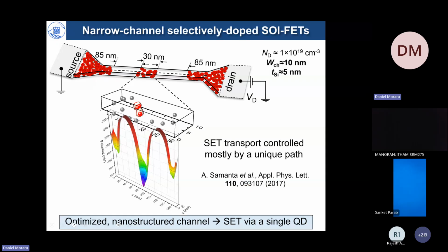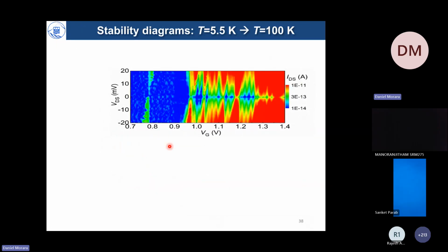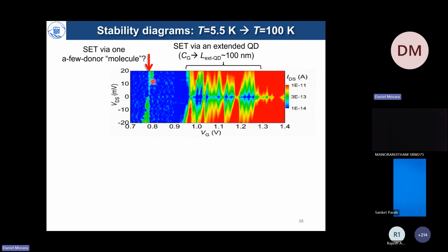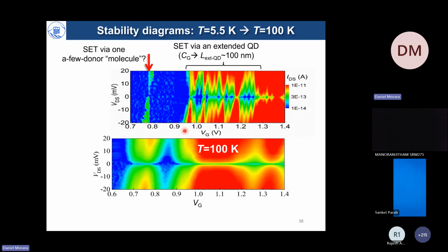So with this optimized and nanostructured channel, we actually started to measure the stability diagrams. By now, hopefully you understand that this is a map of the absolute value of current in the space of VG, gate voltage, and VD. So we observe again these small Coulomb diamonds from extended quantum dots, but also we could observe the signature of a very small current observed at positive VG. Now this could be the SET via one few-donor molecule, and we proved that this is actually a current peak by looking at a high temperature, 100 Kelvin, not 5.5 Kelvin as in the first map. If you increase the temperature, all these fine diamonds are washed out, so we cannot observe them anymore. However, this truncated diamond becomes a clearer diamond in this space at high temperature.